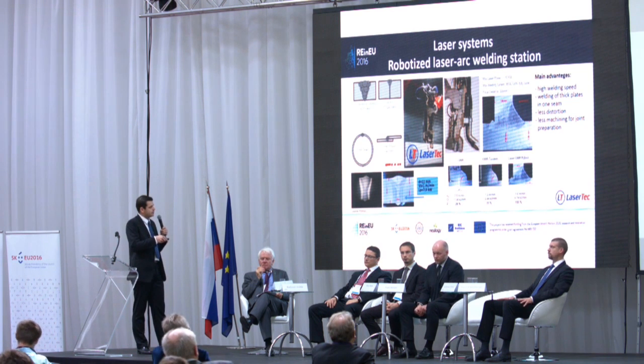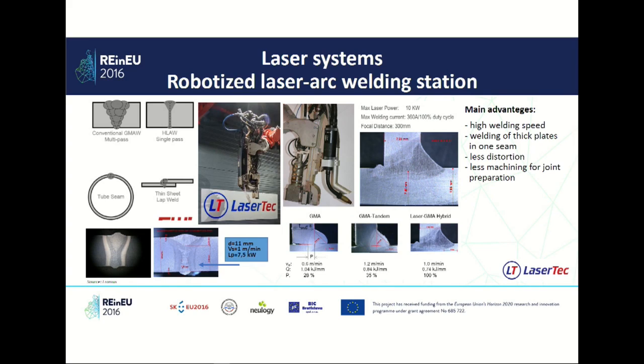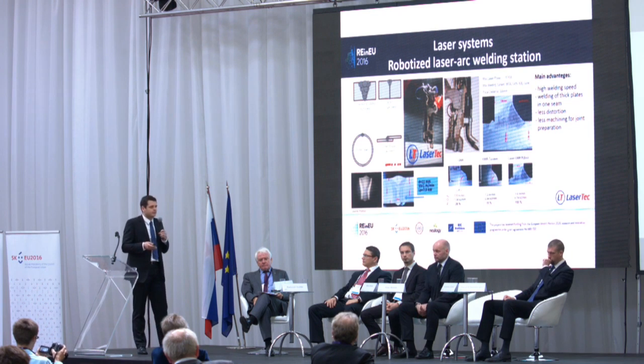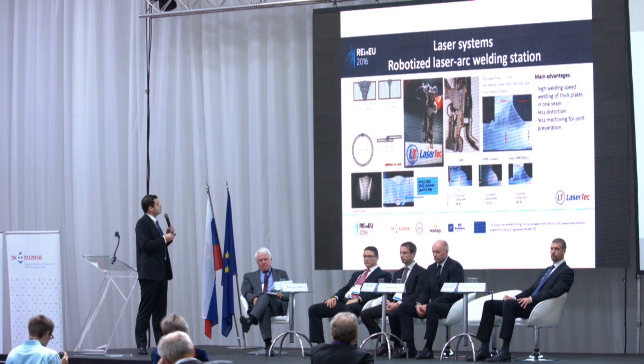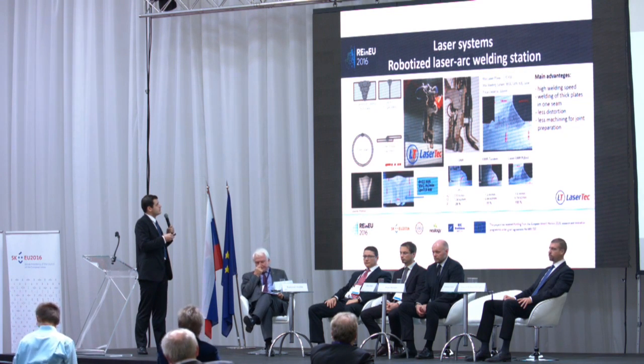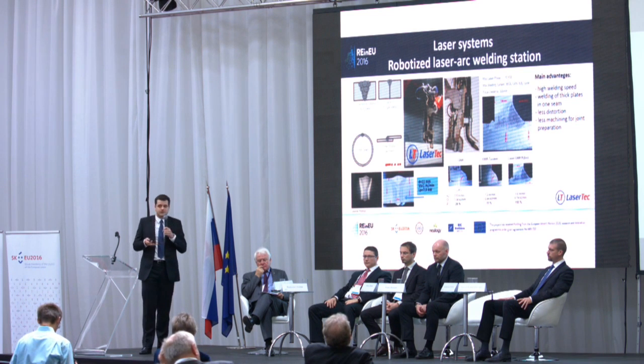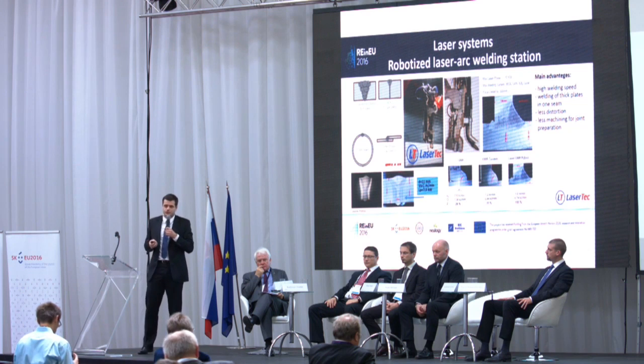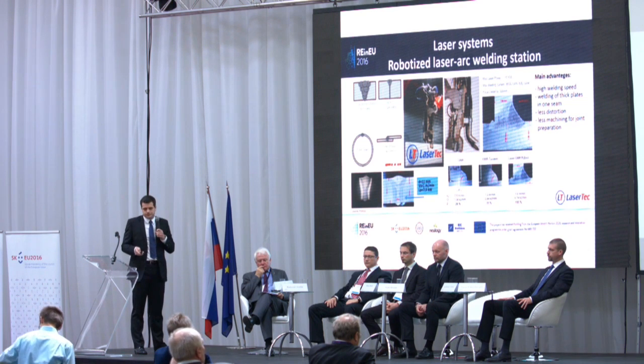As you can see here in the bottom, the comparison for laser hybrid welding is more or less 30% less heat input compared to the arc welding process. So that means less distortion on the component after the process, so you do not have to make additional operations after the welding. Less machining for joint preparation, as I already showed here. Normally you have to do the milling, and now you just prepare the joint like this. So, of course, you reduce the cost of the preparation of the joint.